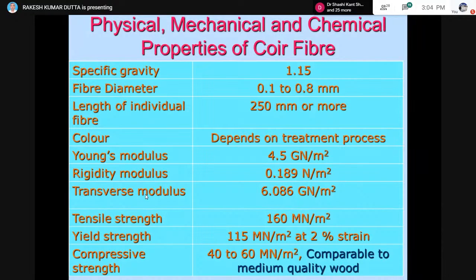How you do the retting operation, and what is the source of the fiber, that gives the color. If it is derived from the matured coconut, it is going to be brown in color, and if it is derived from the green coconut, then white is going to be the color. Young's modulus is around 4.5 giganewton per meter square. Rigidity modulus 0.18 Newton per meter square. I am just giving you this data to tell you that these materials have adequate values of modulus and strength.